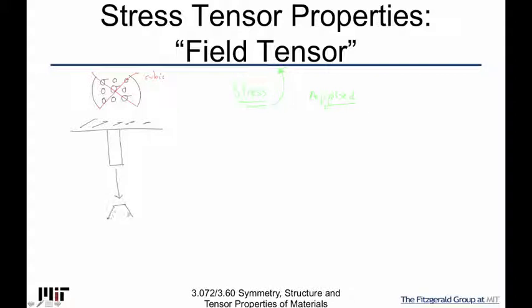And the difference here is that we're talking about that stress is a field tensor. And what that means is essentially it's applied. It's not a fixed property. So, for example, if I'm looking at some property like thermal expansion, that's attached to the properties of that crystal, a symmetry of that crystal. Essentially, when I show a stress tensor like this, I'm applying that.